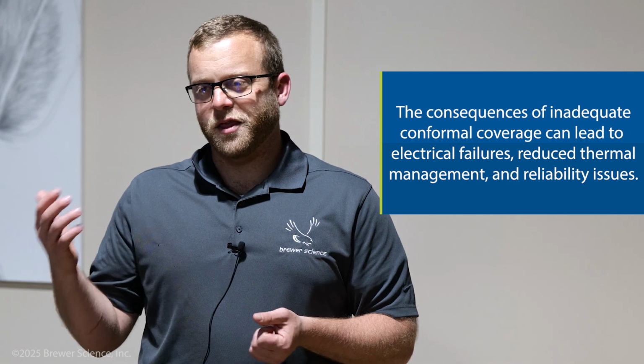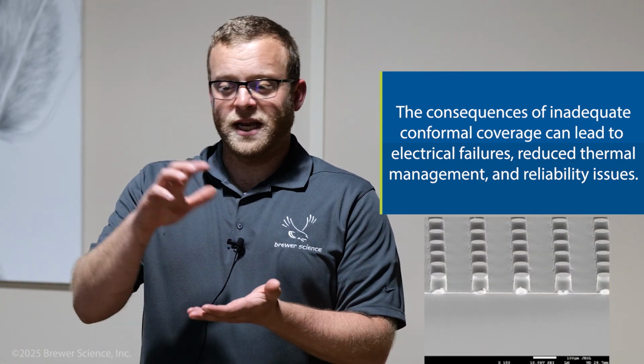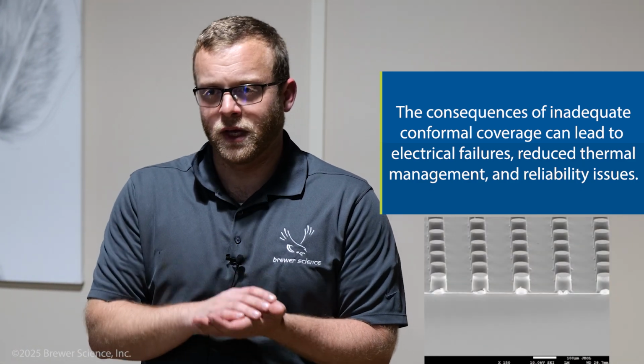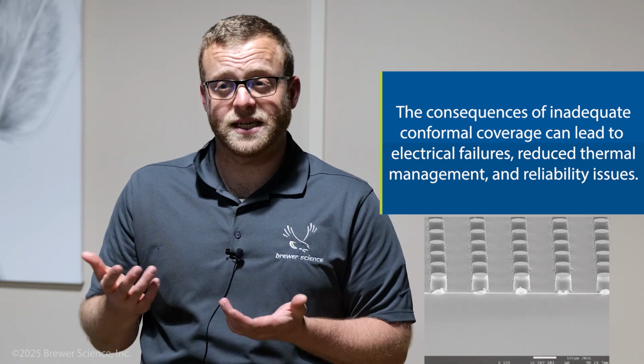In the case of our more recent Versa layer series of materials, we use a thin thermoplastic layer of material to conformally coat over the device features, and then a thicker curable material that adheres well to that thermoplastic material to survive any backside processing those wafer pairs may be going through. Ensuring conformal coverage of the device features enables a much more robust bond line that greatly reduces the chances of delamination during the downstream processing, resulting in ultimately device failures.